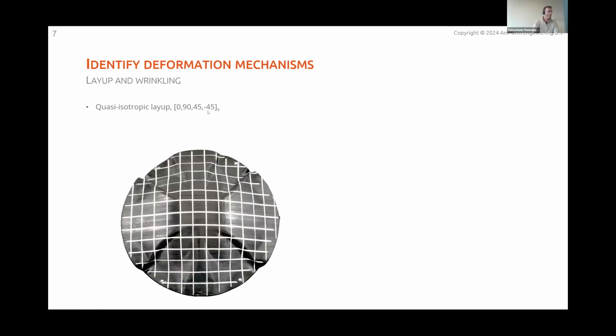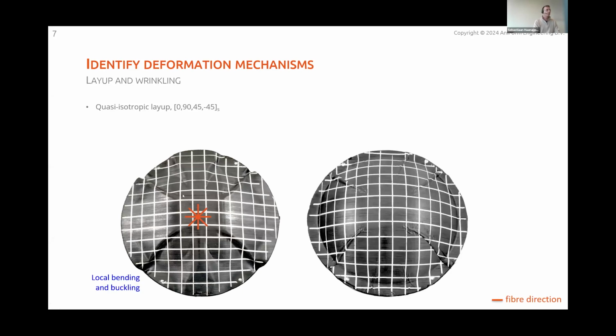Going a step further, this was a cross-ply laminate. Now let's focus on the forming of a quasi-isotropic laminate. That means there's 0, 90, 45, and minus 45 fiber directions in there. And if we form that dome, we get a different result. We see quite some buckling going on. These are, by the way, the fiber directions in that laminate. We see quite some local bending and buckling going on. And if we completely close the press, these buckled areas are pressed into large wrinkles. So there's quite some out-of-plane mechanisms going on, and that means we need to really describe this out-of-plane bending behavior. We need to describe the out-of-plane bending rigidity in the model.